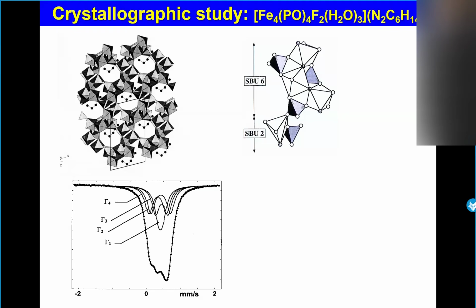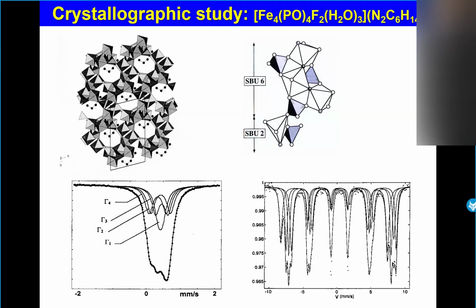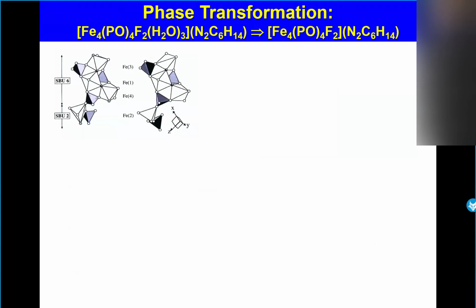In addition, we have the proportions. Without any constraint during the fit, we were obtaining, I do not remember, but something about 25, 26, 24, 25%. That means they were equiprobable, perfectly in agreement with X-ray diffraction. And going to low temperature at 4 K, we can see that we have a phase transition. You can see 4 doublets, 4 sextets, and we can conclude the same about isomer shift and proportions. That means that the Mössbauer spectra were perfectly supporting the results of X-ray diffraction.